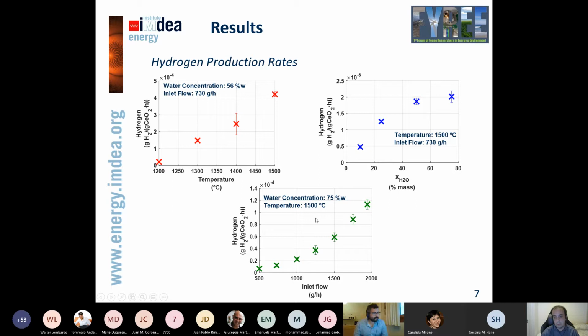What really surprised us a little bit was the behavior of the inlet flow rate on the hydrogen production. That may be because of diffusion issues along the bed and even inside the particles. But we also think it can be an issue if we consider that this is our reacting bed, and we're injecting liquid water from the top, and we assume that not all of it is going to evaporate. It would create a cold area here that will increase as the flow rate increases.